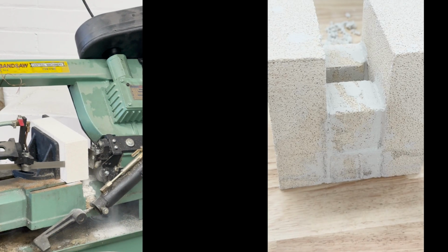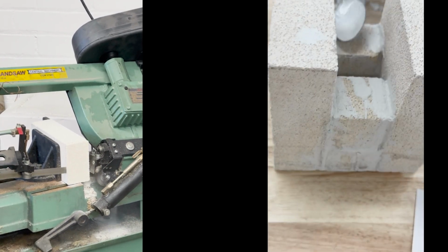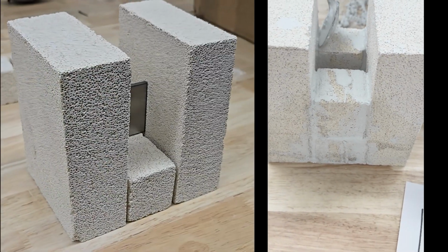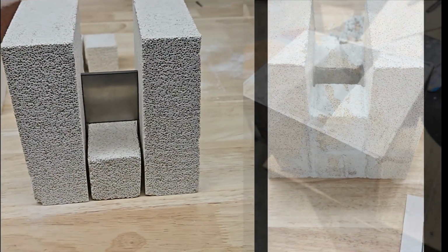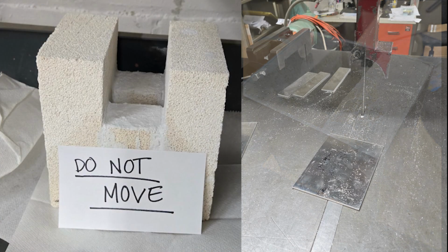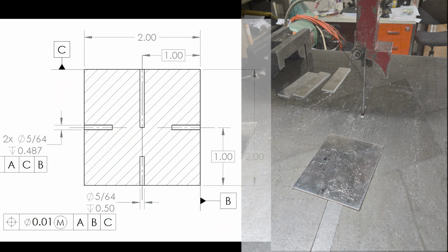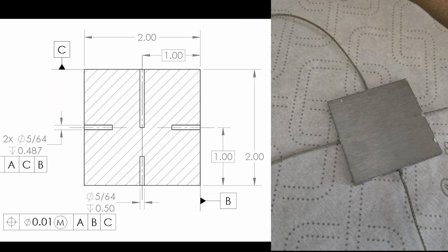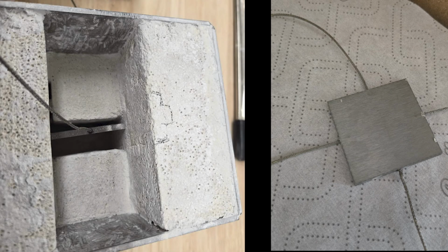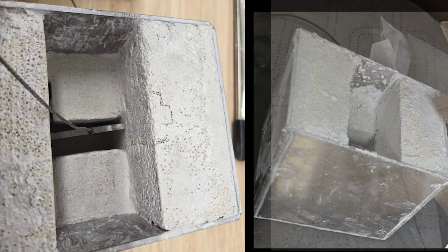To build our test rig, we started with insulated fire brick. We cut it down to the correct size, sanded it for a precise fit, and used insulating mortar to bond the bricks together. Once that structure was complete, we set it into an aluminum frame. For the samples, we had to drill holes to an exact depth to place the thermocouples, which would collect temperature data during the testing. After assembling everything, we ran a rough test and immediately realized our initial design had some serious flaws.